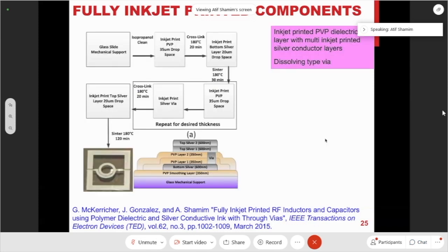So we did a process, without going into much detail. We made an organic ink dielectric, PVP, so you could print one layer, then print metal on top of it, then print another layer or multiple layers if you want. You could print vias, then go to another metal, so you could print multiple layers. What we are doing now is printing the dielectric as well. The typical substrate which you buy from the market, you can also print it. So this now becomes a fully printed system.